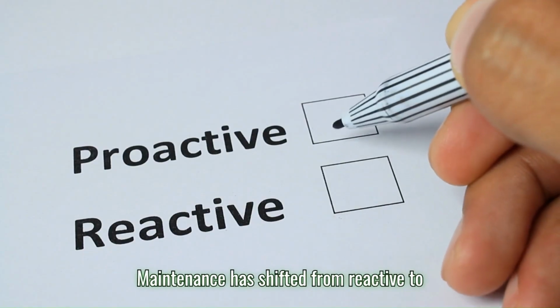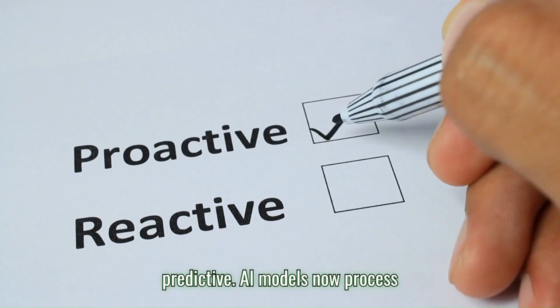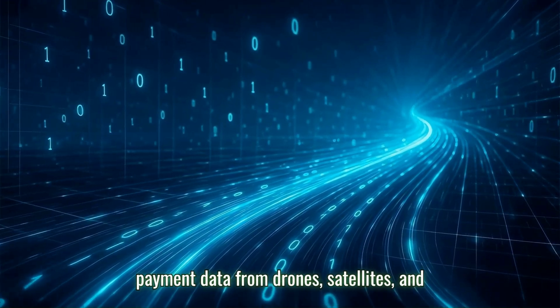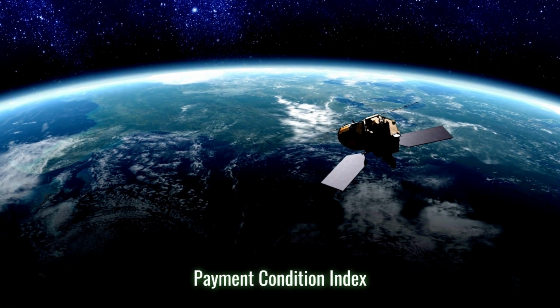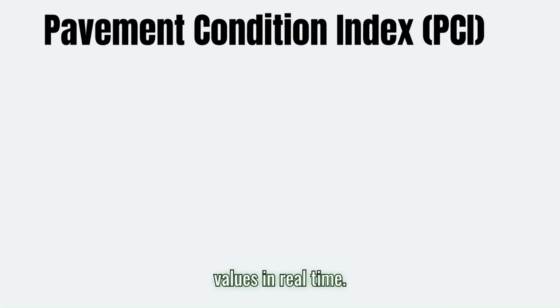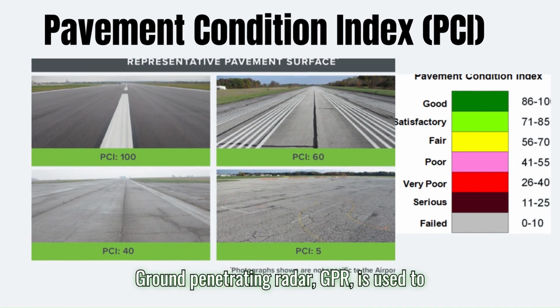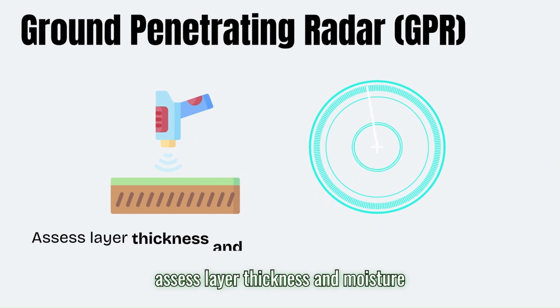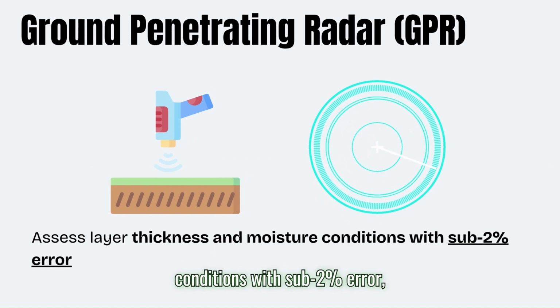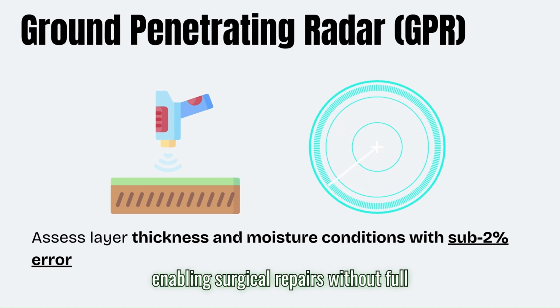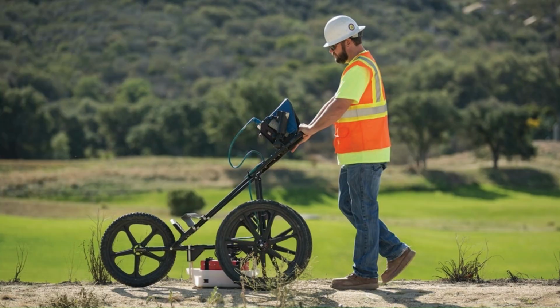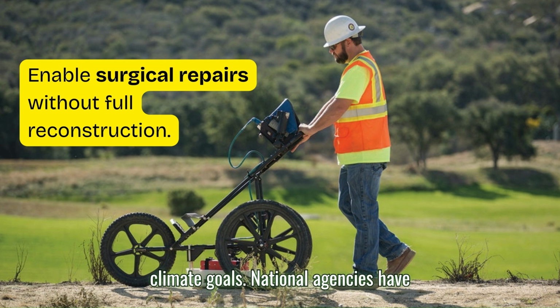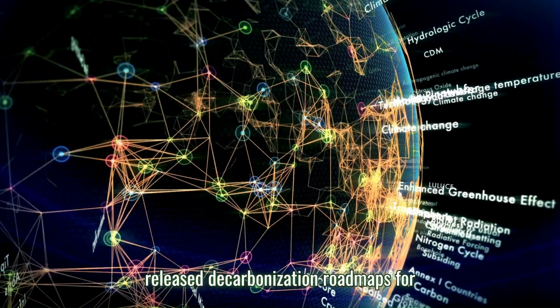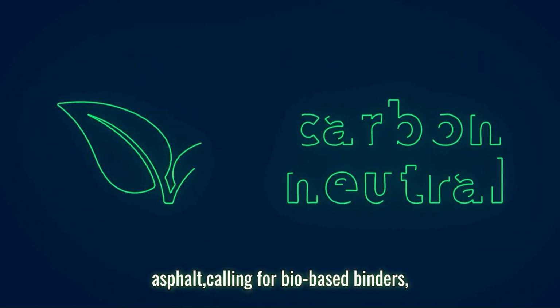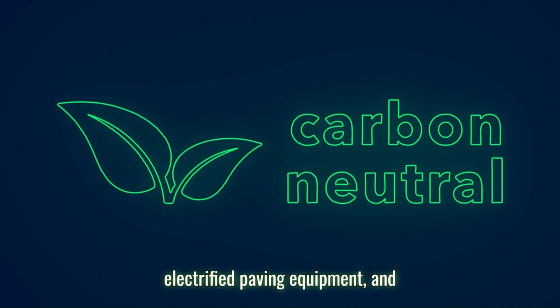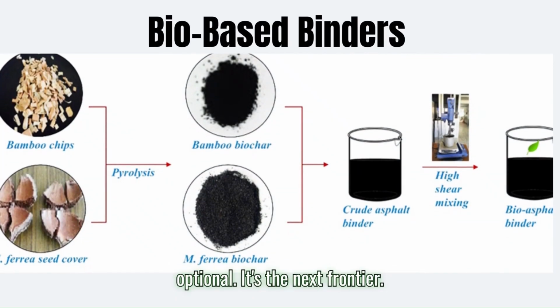Maintenance has shifted from reactive to predictive. AI models now process pavement data from drones, satellites, and embedded sensors to estimate pavement condition index (PCI) values in real time. Ground penetrating radar (GPR) is used to assess layer thickness and moisture conditions with sub 2% error, enabling surgical repairs without full reconstruction. The industry is also aligning with climate goals. National agencies have released decarbonization roadmaps for asphalt, calling for bio-based binders, electrified paving equipment, and low-carbon additives. This isn't optional, it's the next frontier.